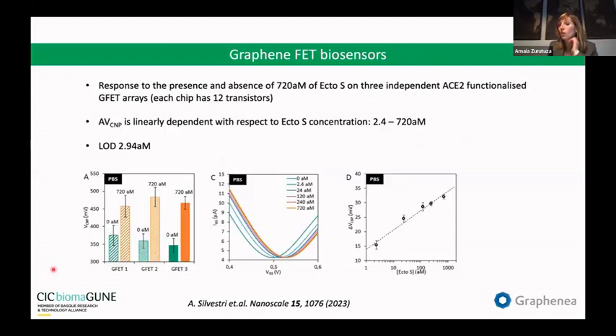Yeah. So these are the results. I told you we could get very low levels of detection. By following the shift of the charge neutrality point, we got a linear dependence, and the lower limit of detection was 3 attomolar. So 3 attomolar is a pretty impressive detection limit for a biosensor. Of course, we didn't use complex samples. Our idea is hopefully to test saliva, so real samples, but this was not done with real samples. The level of detection, of course, is expected to decrease a bit in real samples, but nevertheless, the starting point is pretty attractive, and that's why we think graphene has a great potential in biosensors.